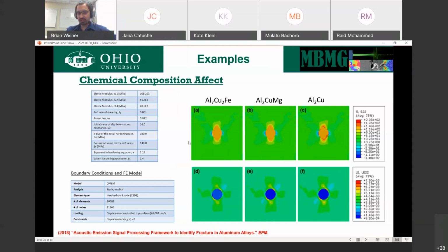What we notice is that for the most part, if we look at the bottom row, we're looking at the strain. There's not any obvious differences. There might be slightly higher concentrations in the case of the aluminum copper in the area around the particle. But we notice the stress in these particles is significantly different. So we know these particles are going to play a role, and that some of these particles are going to carry higher loads than others. So the question is, are some of these critical to its behavior?